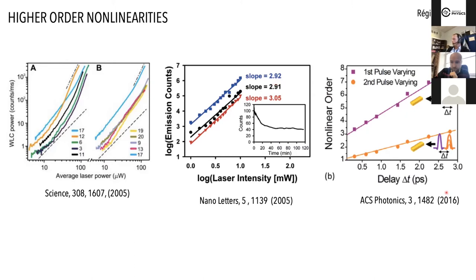And then this 2016 paper that we published together with Regis Meja, who was a postdoc in our group, where he also measured, I'm going to come back to this graph a little bit later, very high nonlinear order, as you can see here, up to 8. Okay, as in a two-pulse experiment, pump and probe, varying either the pump intensity or the probe intensity, you can end up with very high nonlinear orders when things are a little bit delayed between the two pulses. And of course, this interpretation is difficult to reconcile with multi-photon absorption.